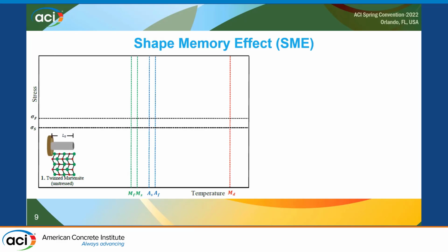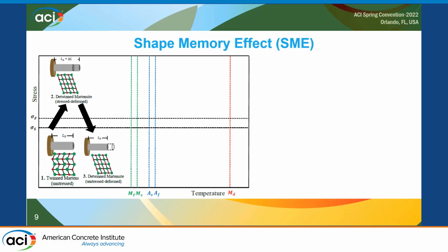Now, shape memory alloys have 2 different states. One is the martensite state, which is the low temperature, high stress state, and the other state is known as austenite, that is the high temperature, low stress state. I'm going to describe these 2 states here. In the first figure, we can see the twinned martensite state when the bar is unstressed. And if we put on some stress, it turns into step 2, that is detwinned martensite, and the shape is deformed. And when the stress is removed, it remains in the detwinned martensite and deformed state.